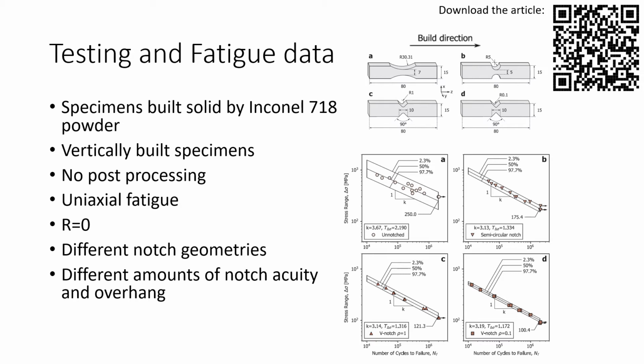So we have a notch geometry, semicircular notch, and V-notch specimens with different notch radius. And the specimens were built from Inconel 718 powder, and they're solid, no internal structures. Specimens are built vertically, and no post-processing has been done, so these are in the as-built state, and they were subjected to uniaxial fatigue with a loading ratio of R equal to 0.